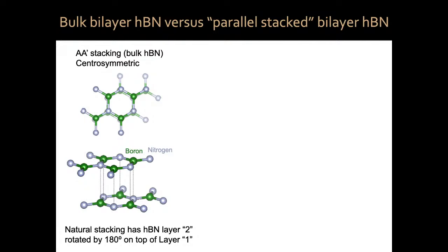So they form a honeycomb layer. Now, if you have two layers of boron nitride which have been extracted from a bulk crystal of boron nitride, it turns out that the second layer is rotated by 180 degrees on top of the first layer. That's the natural growth of this material. And this thing is centrosymmetric. It's not a polar material. It's not a ferroelectric material. It doesn't have a permanent electric dipole moment.